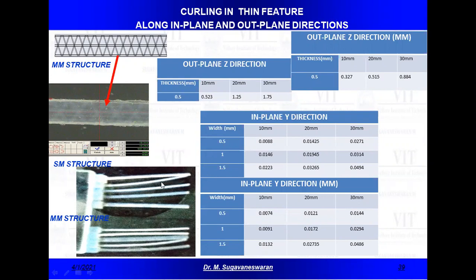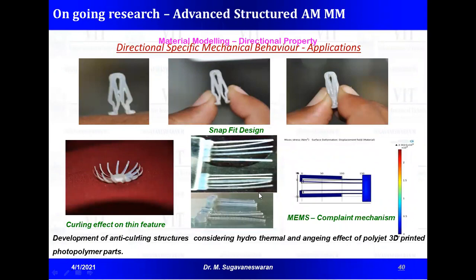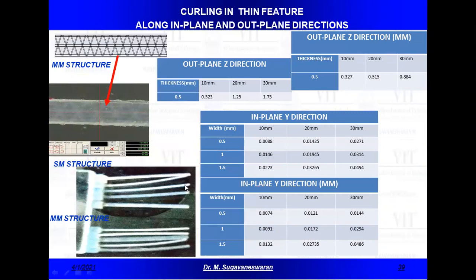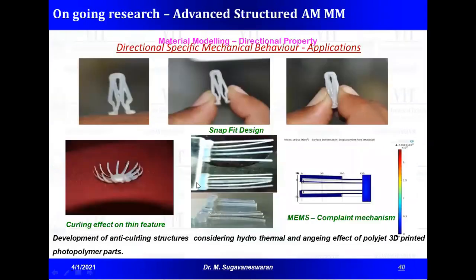is, anti-curling behavior has to be implemented, so that even after the removal of component it maintains the proper position without any deformation. So this type of structure will play a major role, especially in compliant mechanism. Nowadays we are seeing a lot of application of additive manufacturing in compliant mechanism, topology optimization, thin structure, cellular structure fabrication. So we believe that by optimizing the material distribution from bottom to top based on the variable elastic modulus, we could restrict the distortion in thin feature.